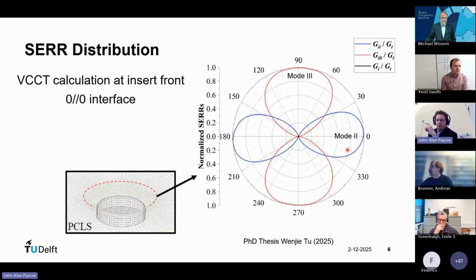I think the interpretation of this calculation is debatable, right? This is the calculation around the border of the Teflon inserts before anything has happened. Purely global modes according to VCCT. So we can have a long discussion about how we should interpret this exactly. But if you do that, then you see there's a mode 2 region, there's a mode 3 region, and then there's a mixed mode region. And of course, in this mode 3 region, it's immediately migrating, and then, is it still mode 3? What exactly should it be? You do not have the situation that's being analyzed here anymore for sure. So you'd have to reanalyze what exactly is going on there. But yeah, that's indeed what seems to be going on.